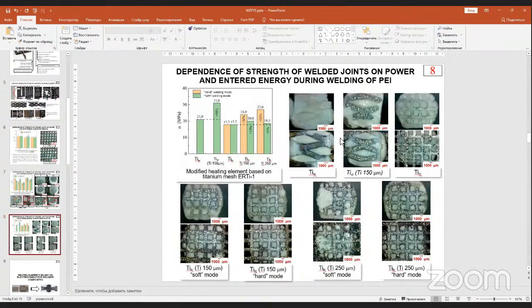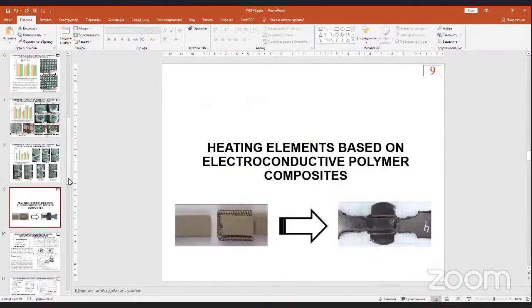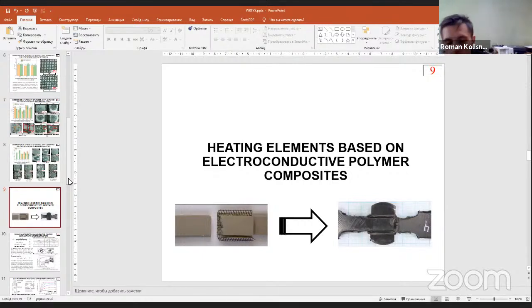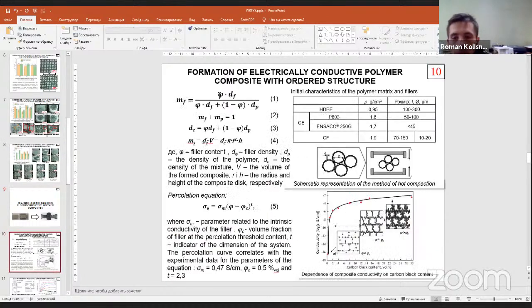Also, we used a metal mesh made of titanium. As you can see from the diagram, it also showed an increase in strength of up to 15% in comparison with standard, unmodified metal mesh. But an increase in strength of 13% did not satisfy our demands. So we transferred to heating elements based on electroconductive polymer composites made of polyethylene filled with electroconductive carbon black and carbon fiber.